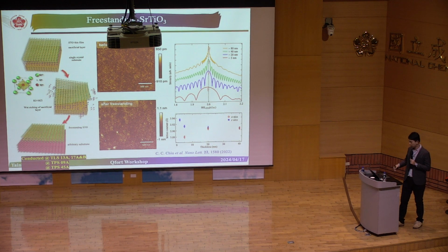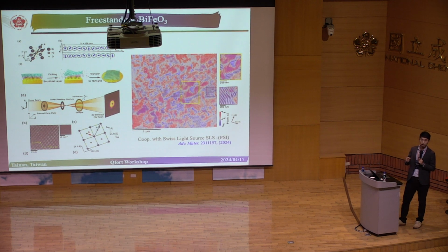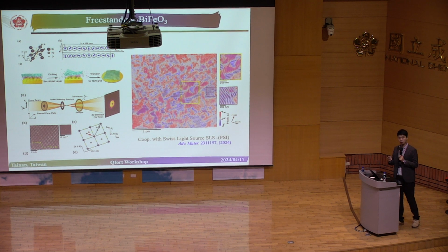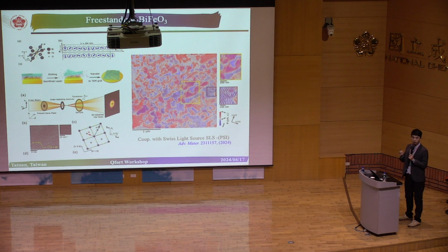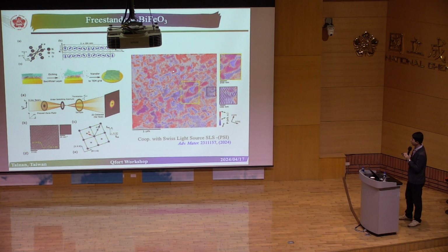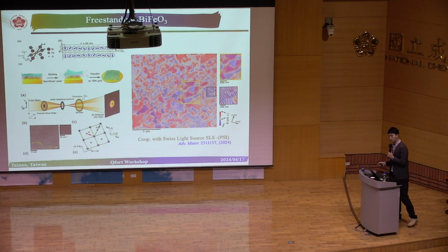Also, to get it a little bit further, we helped my colleagues at the Swiss Light Source develop a new ptychography-based, synchrotron-based technique. With the ptychography-based synchrotron X-ray absorption spectroscopy, they can simultaneously resolve the antiferromagnetic cycloids and the ferroelectric domains. It just got published last month. But today we try to go a little bit further, beyond low-dimensional complex oxides.